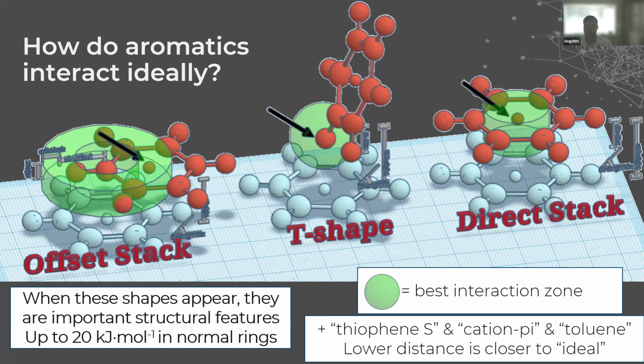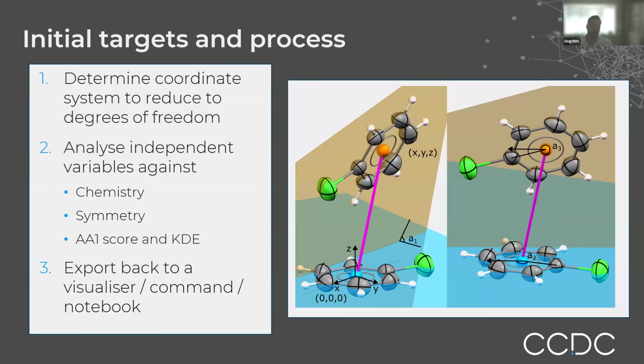Yes, a few different rings are able to be analysed with this tool. So the way that we've designed this tool to analyze aromatic interactions is to simplify a coordinate system to reduce the degrees of freedom, and then we analyze those independent variables against chemistry, symmetry, AA1 score and kernel density estimate. So AA1 score is just a machine learned potential that is trained on DFT calculations for two molecules in the gas phase approaching one another. So a good AA1 score suggests that it's quite a low energy interaction, whereas kernel density estimation is looking at how often those types of interactions appear in the CSD.